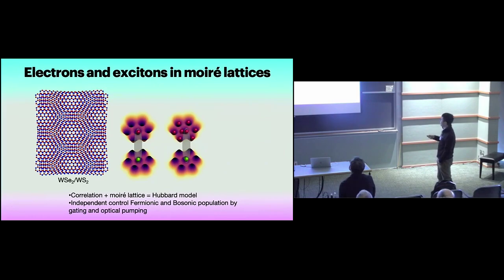So by comparing the energy between this exciton species, X1, and this exciton species we call X2, you can sort of have a feeling of what's the interaction between these two electrons, so you can sort of measure the interactions between the two, the on-site Coulomb potential. This is the rough idea.